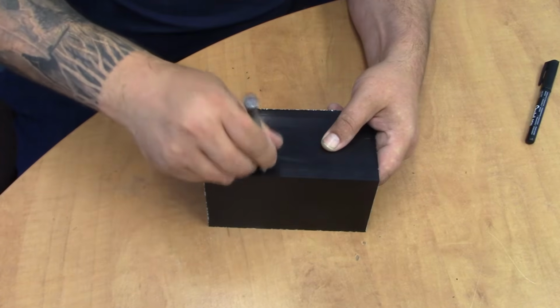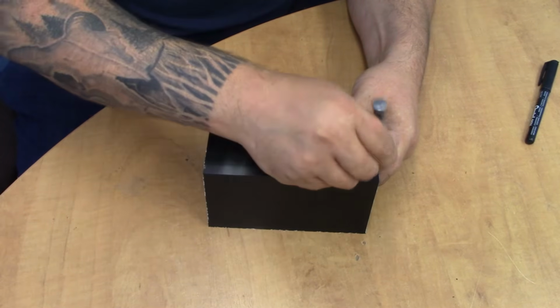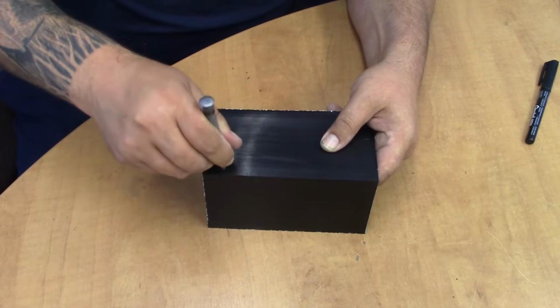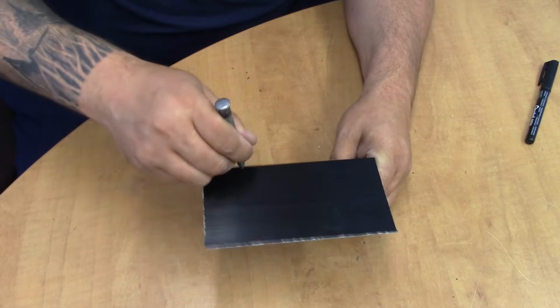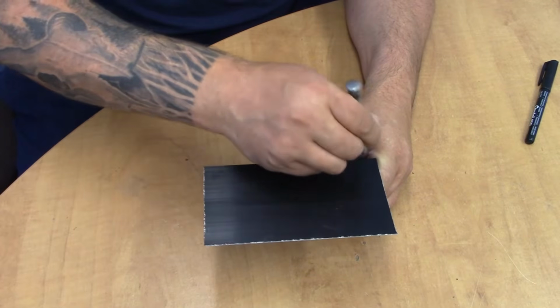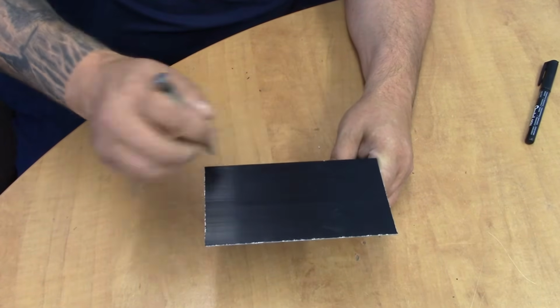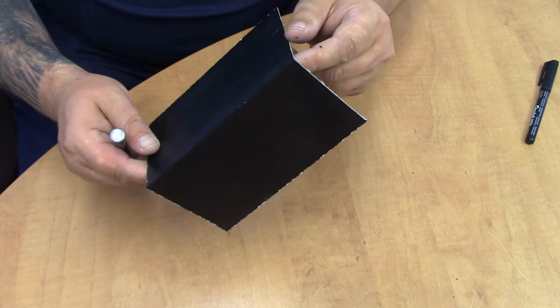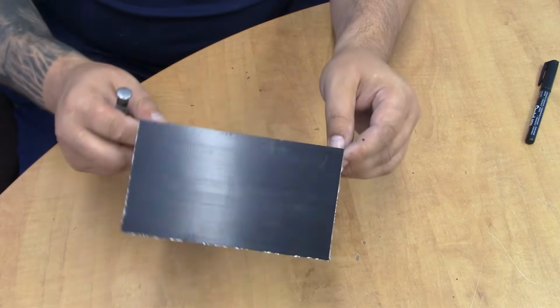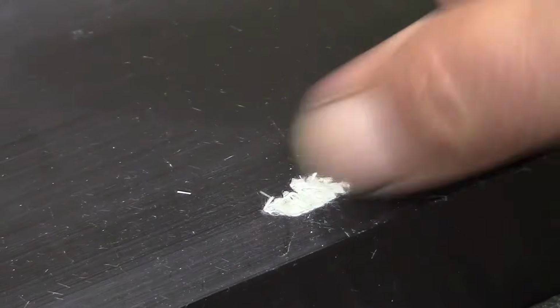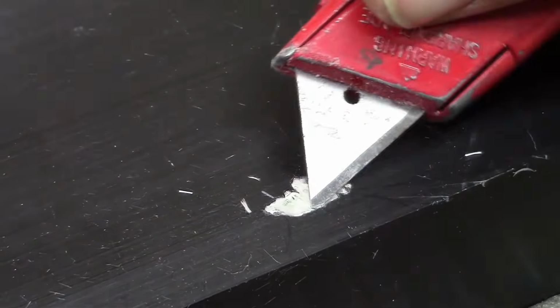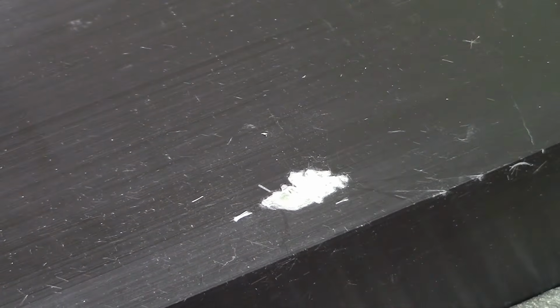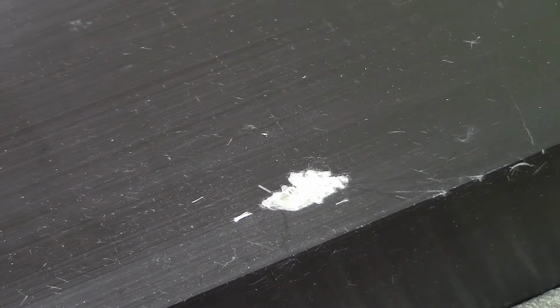One problem you can have with this method is that the polyester resin doesn't tend to create a good mechanical bond between the gel coat and the fine woven cloth, and this can cause the gel coat to eventually peel when weathered, especially if moisture finds its way into the laminate from a cut edge or damage. And this is because the long continuous strands will act like a wick and draw moisture through the laminate. This will eventually promote blistering of the gel coat through osmosis, a lot quicker than a standard fiberglass laminate.